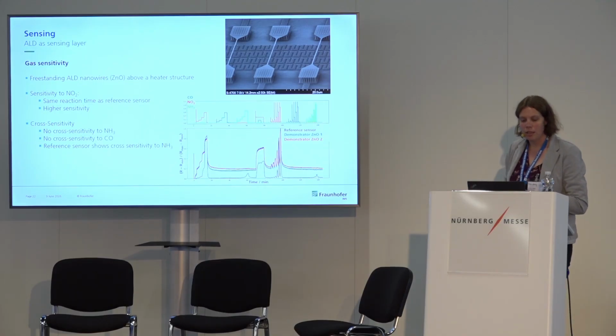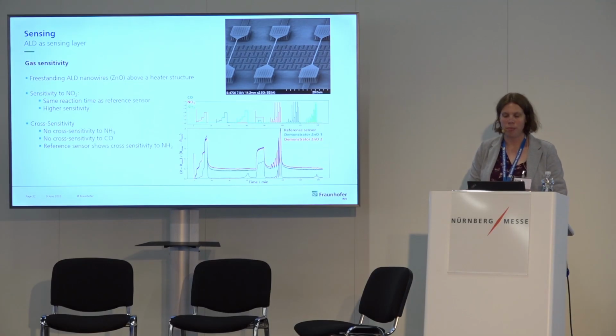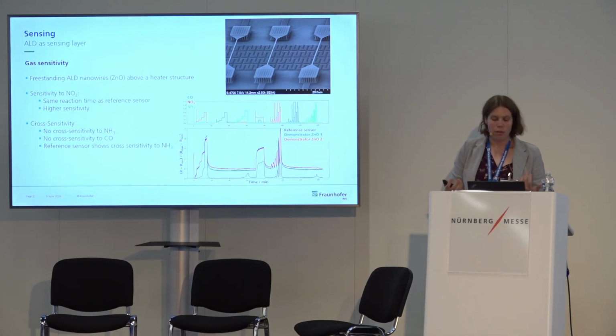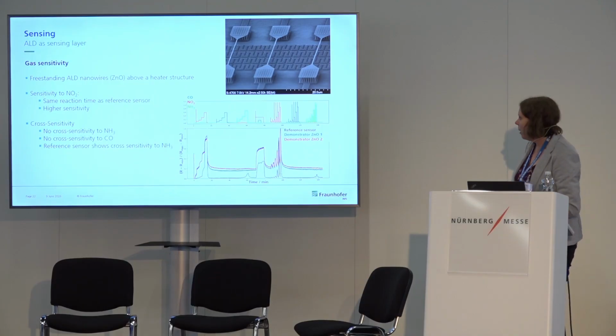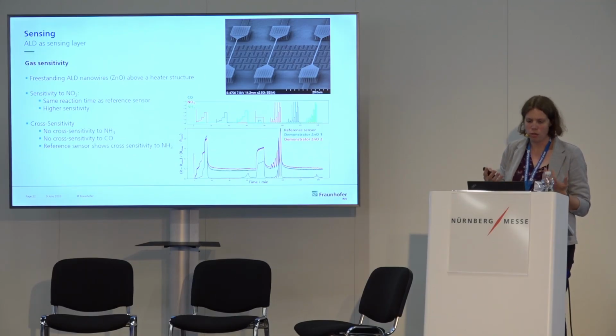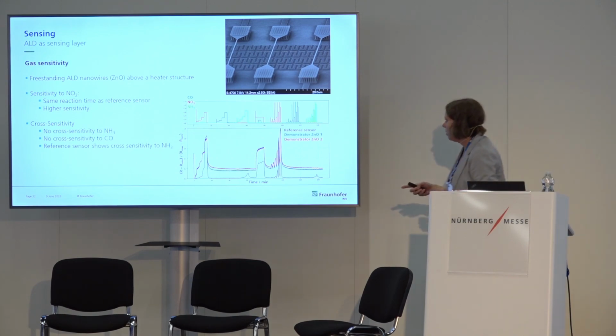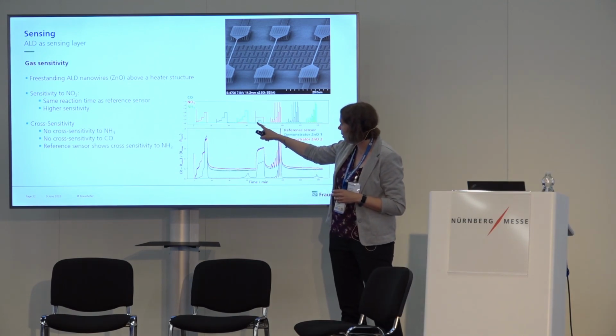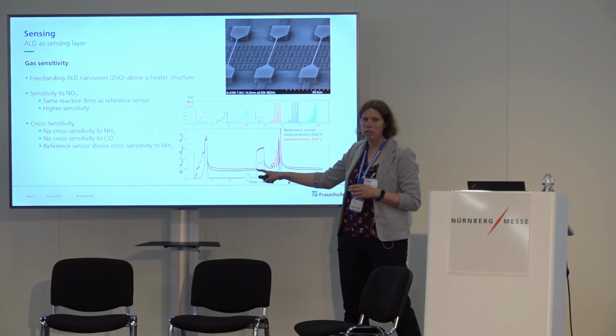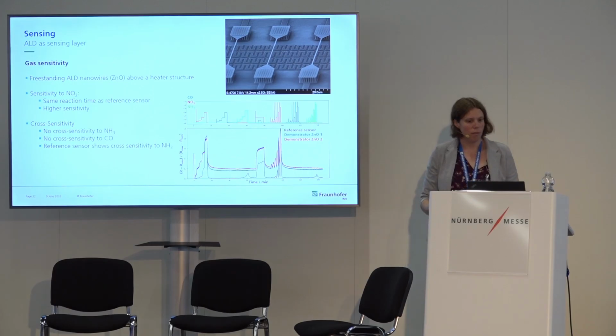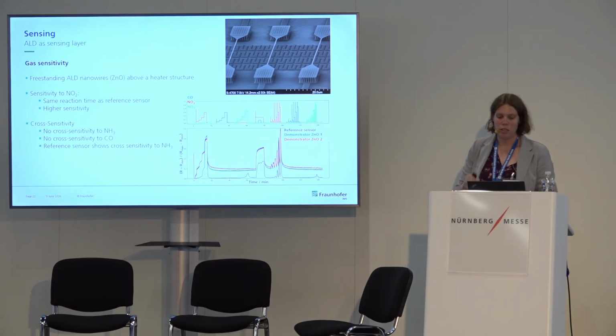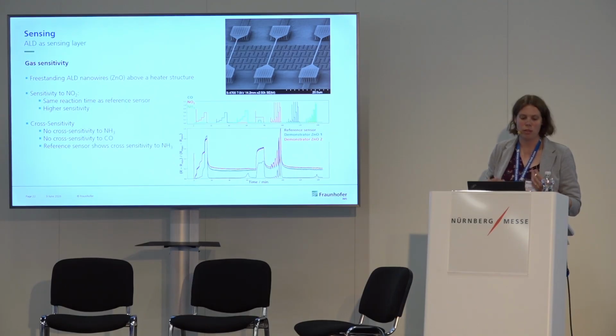And one can see that the reaction time is as fast as for the reference sensor, but this sensor was specially designed for NO2 detection, and lots of the reference sensors have the disadvantage that there are cross sensitivities, as are shown here. So here in green there is the NH3 inlet, and you see from the reference sensor a little peak. So there is a reaction to this other gas, and for our demonstrators, there was no cross sensitivity towards NH3, and also not towards CO.